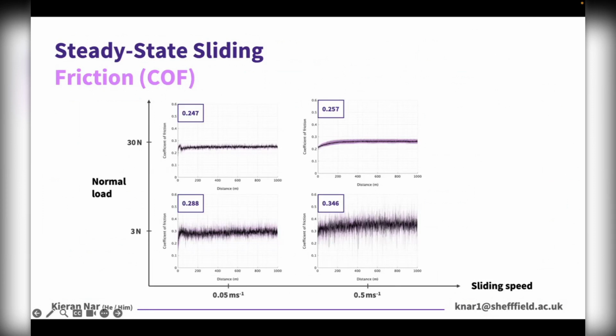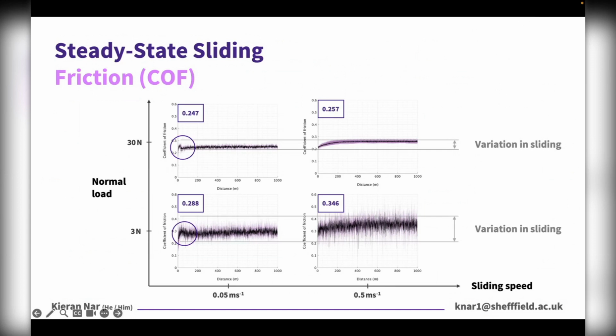So this matrix shows the mean coefficient of friction responses recorded during each sliding condition. Almost immediately, the first thing you'll notice is the differences in variation in sliding exhibited during each sliding condition, particularly based on load. I should have mentioned that this study focused on top surfaces specifically. As you can see in the circled regions, we again saw these initially heightened running friction responses, though this was less apparent for 0.5 meter per second sliding, so higher speed sliding, which suggests that this mechanism is a function of sliding speed.